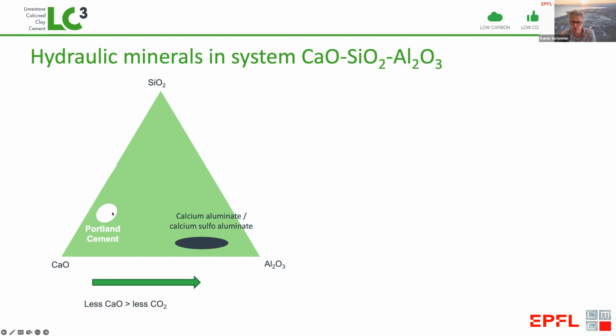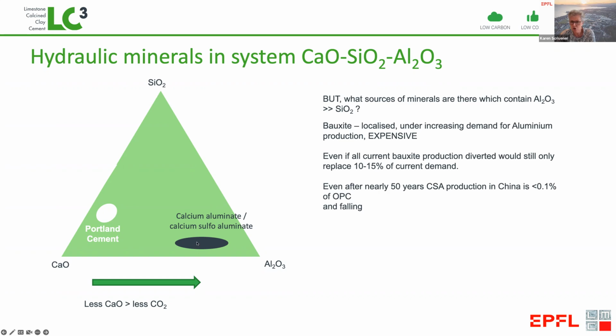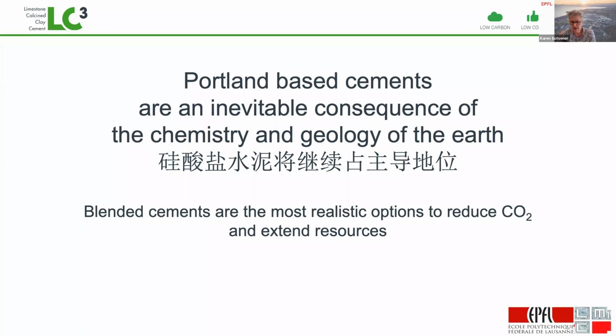And we know in this system, there are basically only 2 regions where we can produce cementitious materials. The regions of the calcium silicate, which is what we call Portland cement, and this region where we have calcium aluminate, calcium sulfoaluminate. At first sight, this looks interesting because it contains less calcium, so less CO2, but the problem is we don't have the minerals we need, which contain much more alumina compared to silica. We'd have to use things like bauxite, which is heavily in demand to produce aluminium. So Portland cements are here to stay, and the best way to reduce CO2 is to replace as much as possible of the Portland cement with other materials.